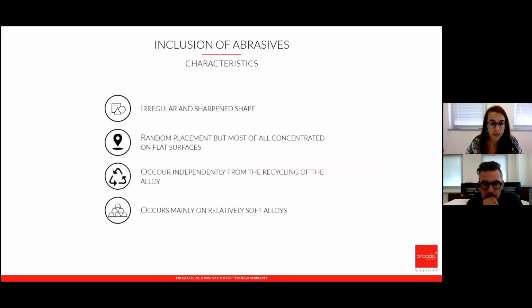So how do these inclusions present themselves? They tend to be irregular and sharpened in shape, and they usually happen when we have very big flat surfaces. Of course, as it comes from the abrasive that we're using to polish the material, it can happen even if we're using completely fresh material. I must remind you that, differently from hard spots, which happen during the melting of the pieces of metal, in this case the pieces are okay after melting, and the defect is caused only during the finishing treatment.